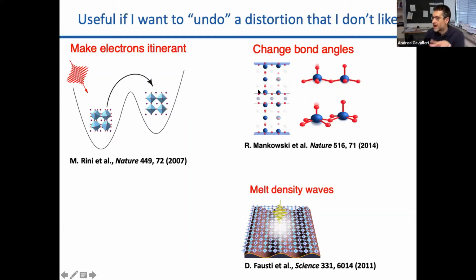We could also change bond angles in other materials, in which we used femtosecond X-ray free electron lasers to validate. And also sometimes melt density waves that are detrimental, for example, for superconductivity, thereby enhancing superconductivity. So in principle, even in the most boring incarnation of nonlinear phononics, where the distortions that I'm inducing are only totally symmetric, I can find situations in which this can be used to our advantage. Again, along the lines of what can be done by applying pressure to a system.